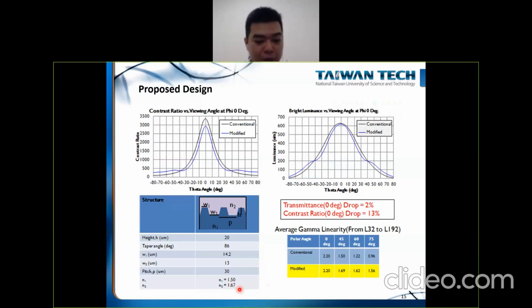You can see that by using this type of structure, we can improve the contrast ratio in the large angle direction. And because your eyes are more sensitive to contrast ratio below 1000, the contrast ratio enhancement from like 150 to 300 will be very significant for your eyes. And then the contrast ratio in the normal direction only drops from about 3,300 to about 2,800. So it's still okay for our application.